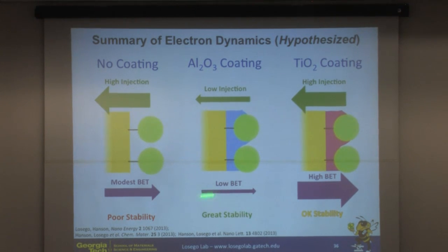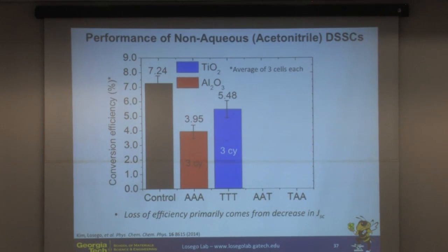Now, as you'll recall, the alumina has great stability. TiO2 has okay stability. So we came up with this very naive hypothesis that, what if we mix the alumina with the TiO2? Could we get sort of a synergy of these properties, sort of an averaging of these properties? Okay, so we actually went ahead and made some dye-sensitized solar cell devices. This is a control device with no ALD coatings. We get about 7.25% efficiency, so reasonable efficiency dye-sensitized solar cells. If we just go ahead and put 3 cycles of alumina or TiO2, we take quite a hit in efficiency, maybe 30% to 50% reduction in efficiency.